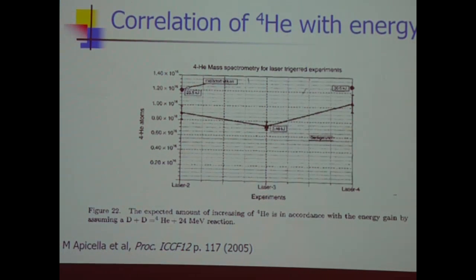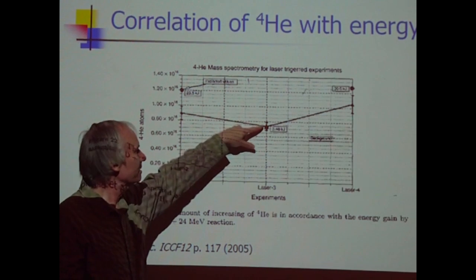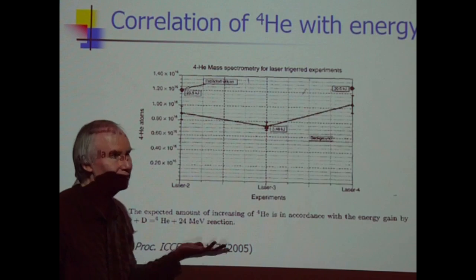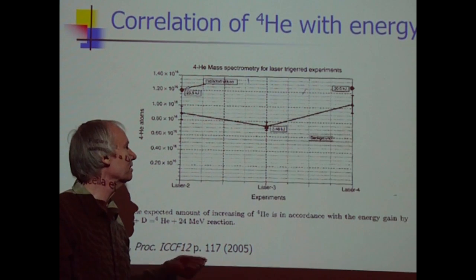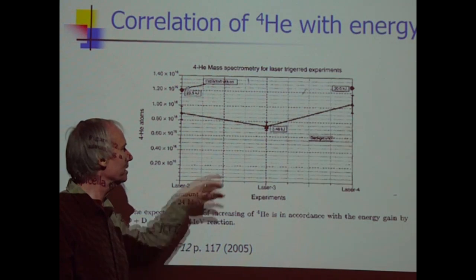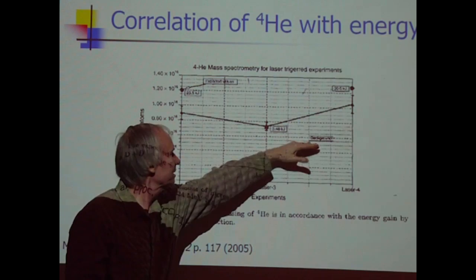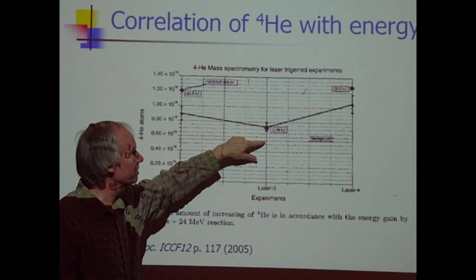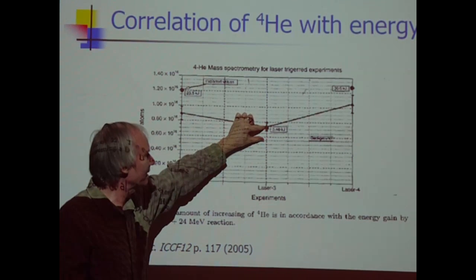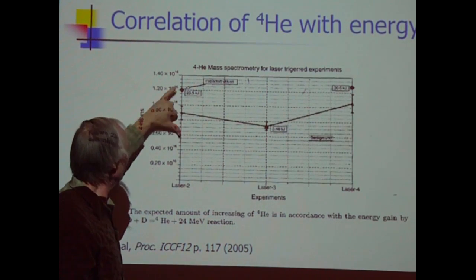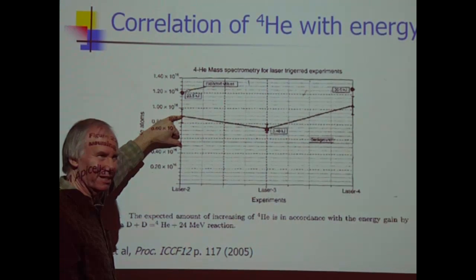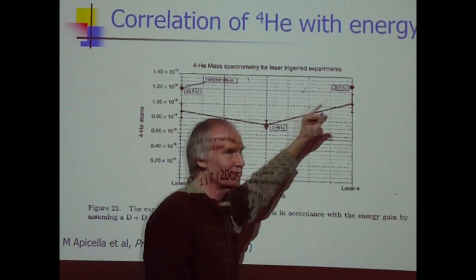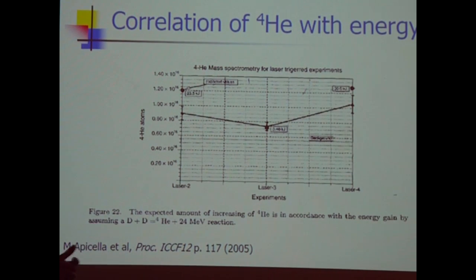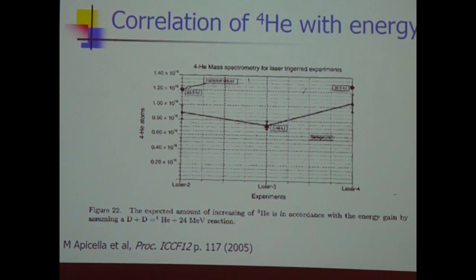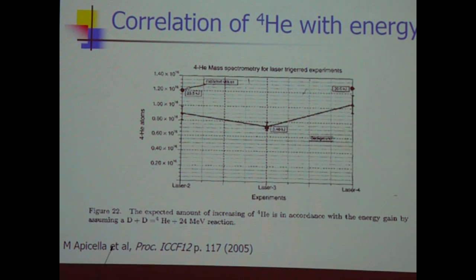But in this experiment, an effort was made to scrub all the helium-4 out. So in this case, the experiment versus the expected value, scrubbing out all the helium-4, gives the 24 MeV number. Now, a problem with this experiment is that there's a line here which says background, and this is the 5.2 parts per million background. So in fact, it's more like this. It's not from down to here, it's from here to here versus here to here. So this, I know this is under 60%, and this is maybe 60%. So these numbers are close to the others. But this one, again, you scrub out the helium, you see it. So there are now 2 such measurements. There are no resources, in all this time, to do more measurements.